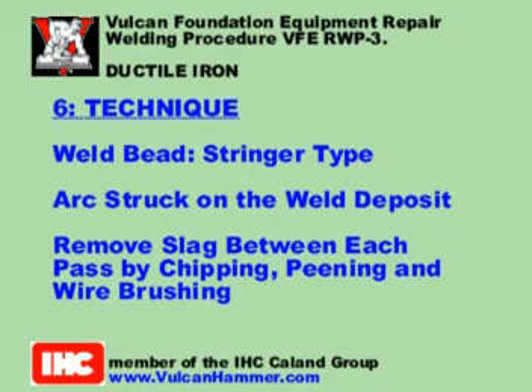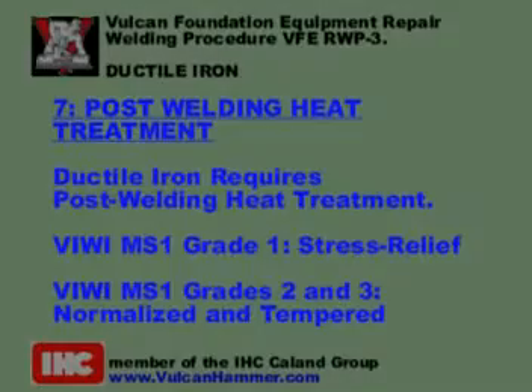Section 6, Technique. The weld bead should be of stringer type. The arc should be struck on the weld deposit whenever possible. The slag should be removed from the weld deposit between each pass by chipping, peening and wire brushing. Section 7, Post-welding heat treatment. All ductile iron castings should receive a post-welding heat treatment.